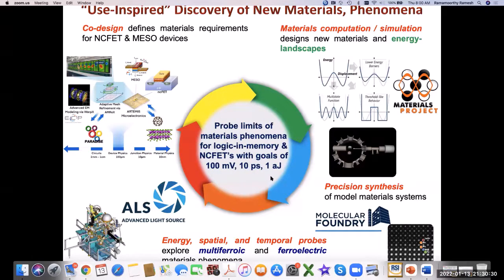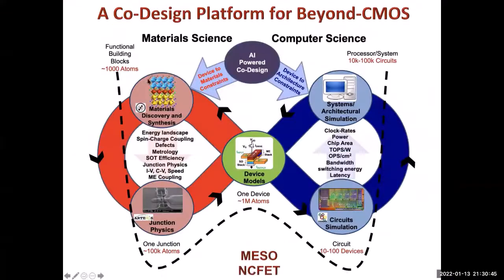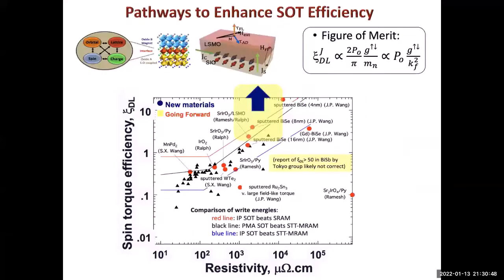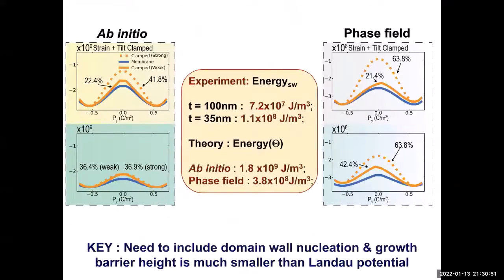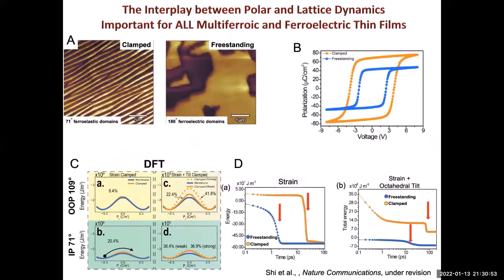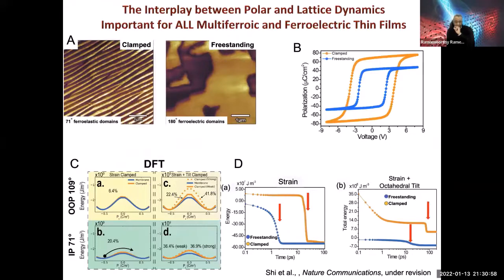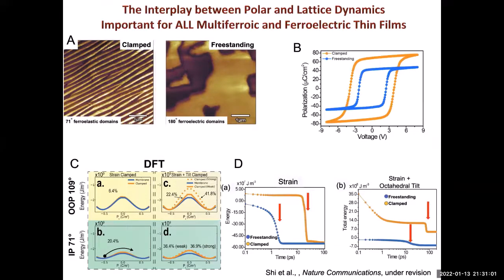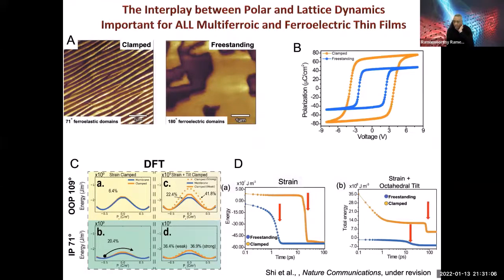Hi Ramesh, very nice talk. You presented a lot of data, so I'm not sure whether I missed it, but you spoke of the clamped films and the freestanding ones, where the domains in the clamped one were 71 degree domains, whereas the other one had 180 degree domains. Do we have an understanding why the strain was so large that the domain structure changed so much?